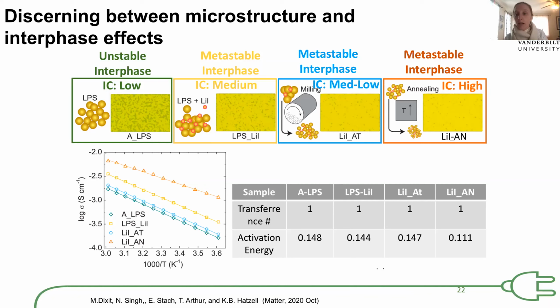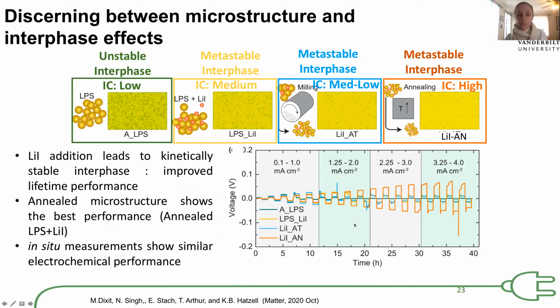All samples had a transference number of 1, which is unsurprising, and a pretty low activation energy for transport. We did stability tests where we stripped and plated lithium metal in a sandwich symmetric cell. Again, we saw that our annealed samples had the most stability, whereas our sample with the unstable interface failed fastest.